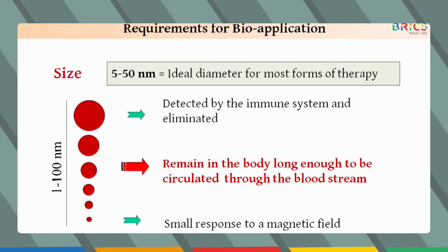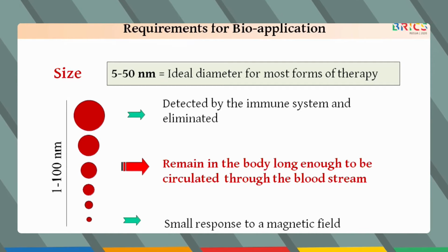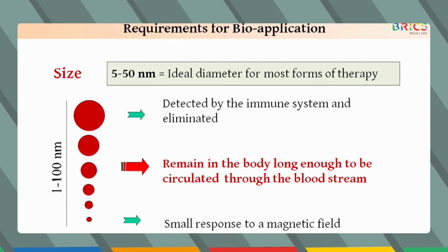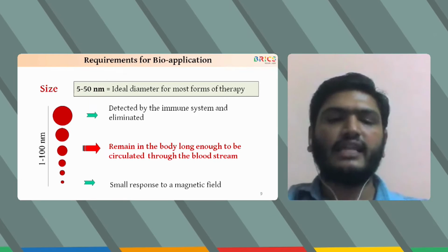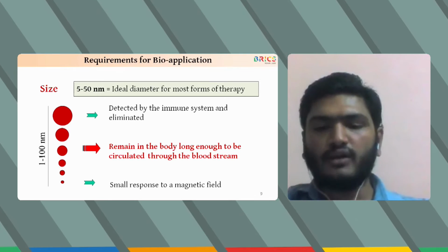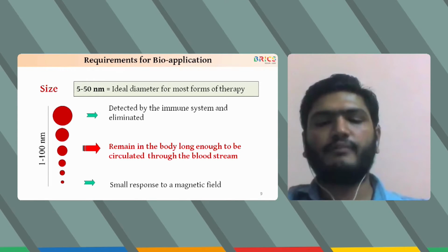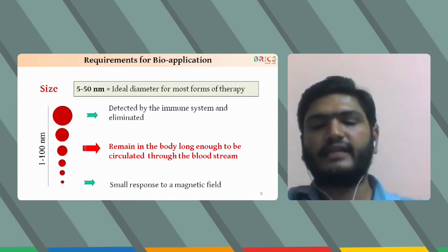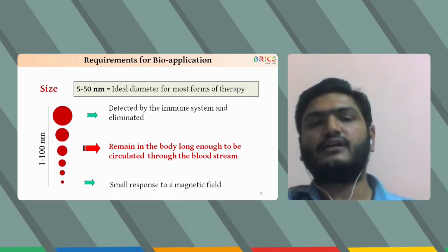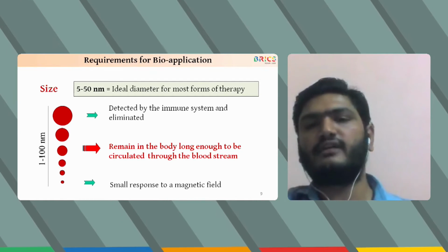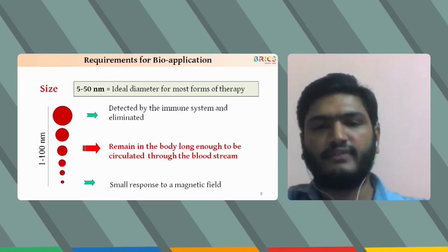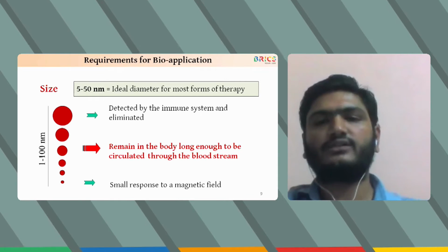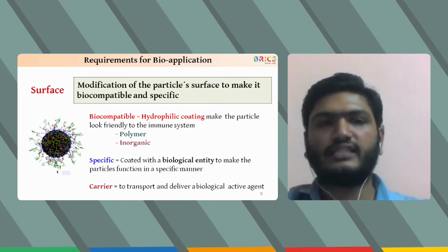So the size is the important thing for the magnetic nanoparticles. If they are too big, then they can be detected by the immune system and eliminated. If they are too small, then they can be non-responsive to the magnetic field. So the ideal size of the magnetic nanoparticles should be between 5 to 50 nanometers. With this size range, they will remain in the body long enough and can be easily circulated through the bloodstream.